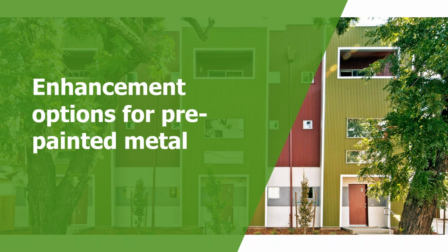We've not seen, once installation is done, much difference in performance versus warmer weathers. The one thing we do run into in cold weather is the actual forming of the metal. When a fabricator has got coil and they're forming panels, if it's done in cold weather, there can be issues. The paint might crack or undergo a phenomenon that we call hazing, where you get a blushing effect on the paint until it warms up again. So not too many issues once installed in cold climates, but anyone who's roll forming products in a cold climate needs to use some caution. A lot of those guys actually use infrared lights and heaters on their equipment to warm the steel and the paint up a little bit before they form it to avoid those problems.